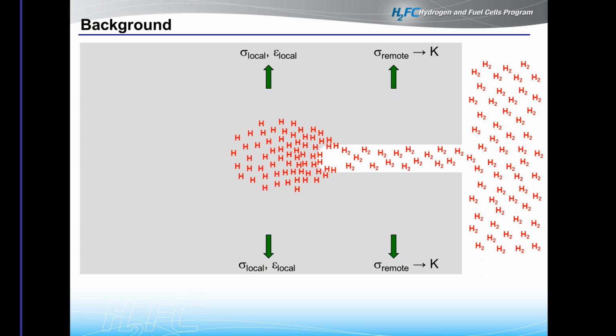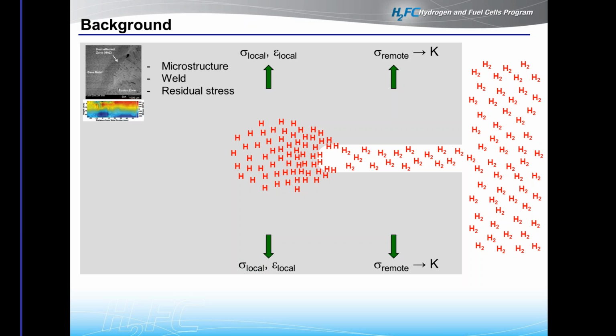in this embrittlement effect. So the three variables that we're going to look at first is related to, once there's hydrogen in the material, how does it interact with the microstructure? In particular, we're going to look at some welds and really the role that residual stress can have, because anytime you're talking about welds, what you're really introducing are potential changes in residual stress. The other area that we're going to look at is the effect that microstructural banding can have on hydrogen embrittlement. And banding is not necessarily desirable. It definitely is not a desirable microstructure, but it does give us the opportunity to examine how different orientations behave if we propagated the cracks in different orientations.